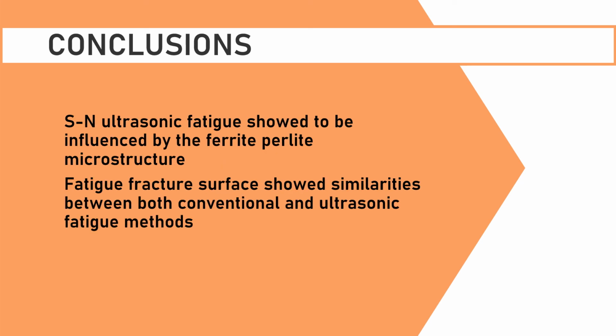By observing and comparing all performed fatigue tests in conventional methods and in the ultrasonic methods presented in this work, in two different states, the uniaxial tension compression state and the multi-axial tension compression torsion state, we can clearly see that the ferrite microstructure had an influence in the results, the material showing to be sensitive. High frequency testing led to a much higher stress for the same life and no failure in a very high cycle fatigue regime. Then comparing the fracture surfaces and fracture angles of both stress state specimens, we can see similarities between both methods, showing the same stress state being applied and creating the fatigue damage.